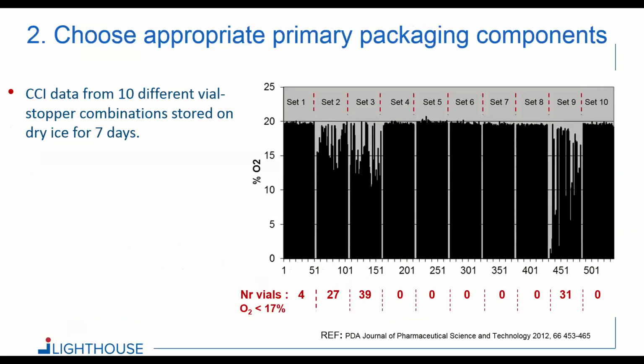Number 2, choose the appropriate primary packaging components. So here is a data set from 10 different vial stopper combinations. These vial stopper combinations were stored on dry ice for 7 days. But here we are actually using an oxygen measurement. So if you go back to that original media fill example where we showed that different headspace measurements can be used as a CCI test method, here you're looking for samples that have depleted oxygen levels, which are an indication that CO2 has come into the vial and displaced the original air headspace.